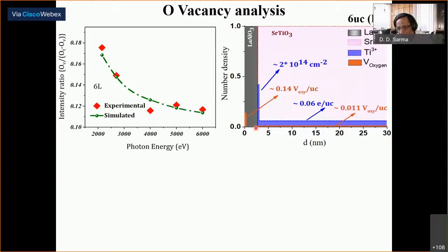Likewise, this vacancy that I find throughout the strontium titanate is about 0.01 vacancies per unit cell. That will give me about 0.02 electrons. And the number I get is 0.06 electron, in the same ballpark. Remember, these are two completely different, independently evaluated quantities. To see them in the same ballpark gives us confidence that it is this oxygen vacancy that gives these electron